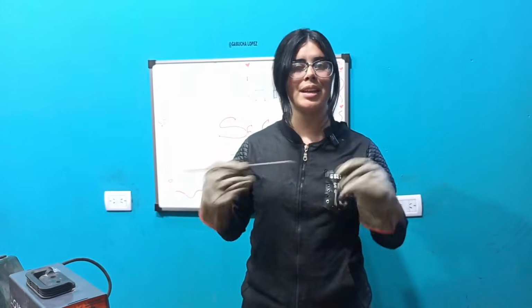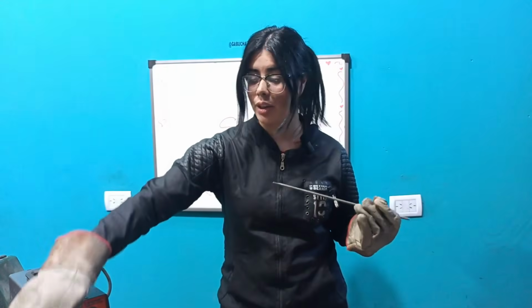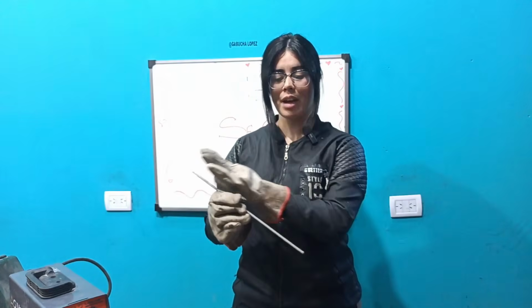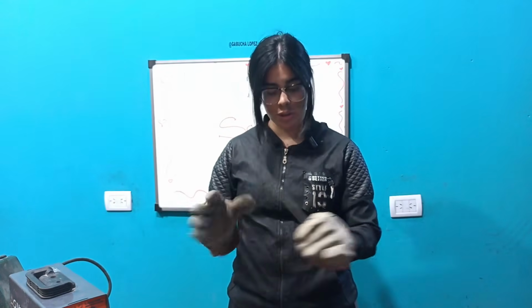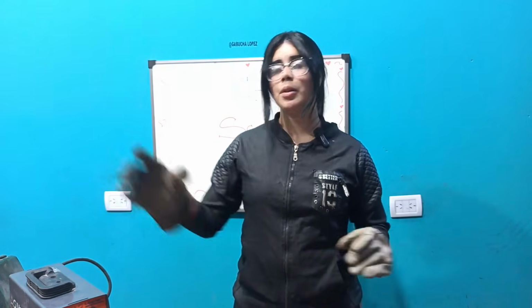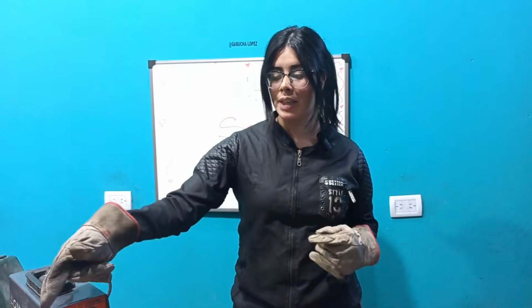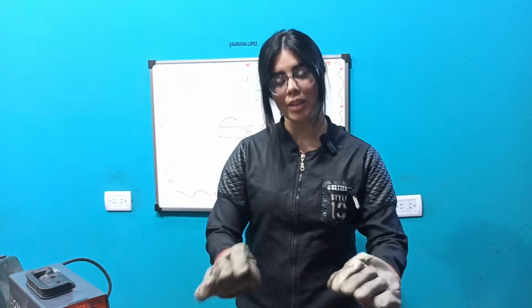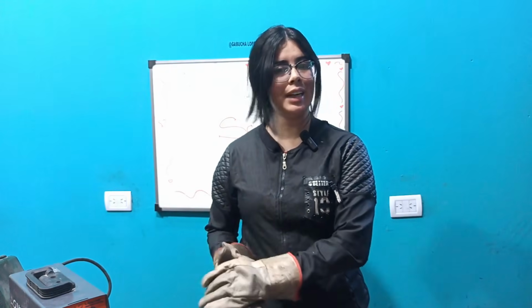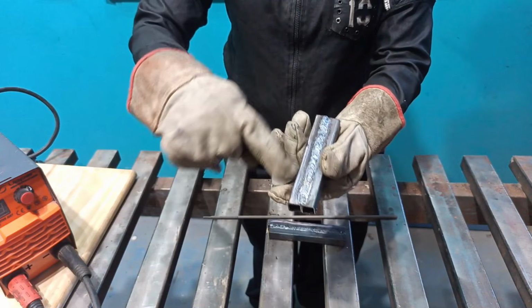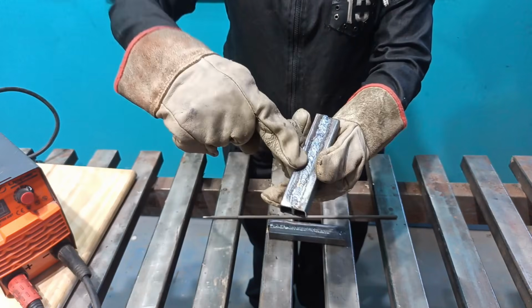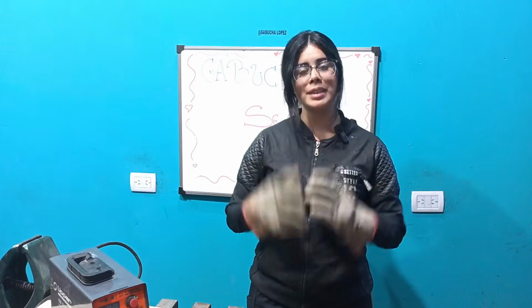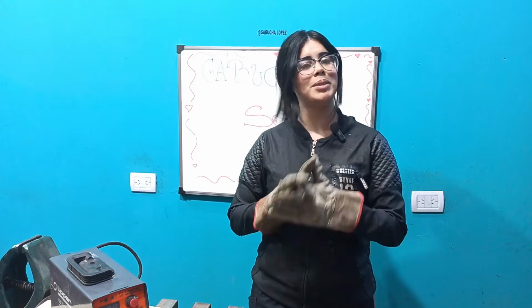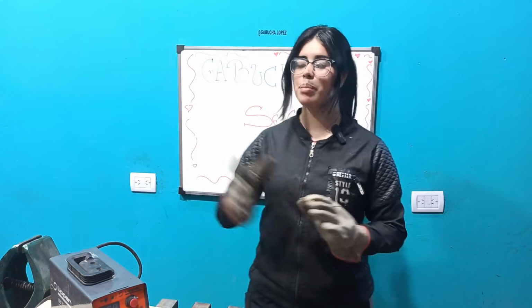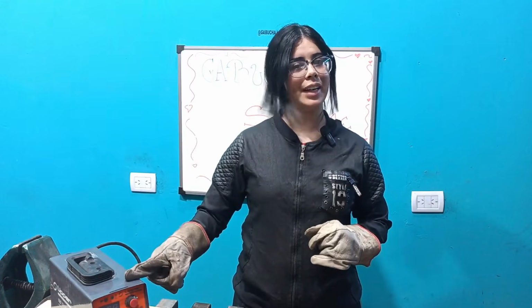When we weld with reverse polarity, which means the electrode holder clamp is on the positive, 70% of the heat goes to the electrode and 30% to the material. And when we weld with direct current, which would be putting the electrode clamp on the negative, it would be the opposite. 30% of the heat would go to the electrode and 70% to the material. That's why, since there's more heat in the material, the weld penetrates deeper into the material. When we need to make a penetration bead, we are going to use direct. That would mean putting the electrode holder on the negative side.